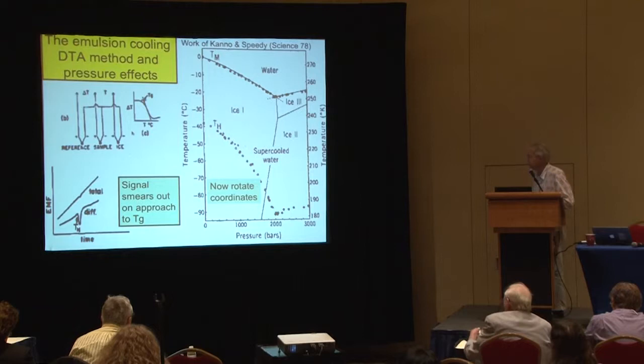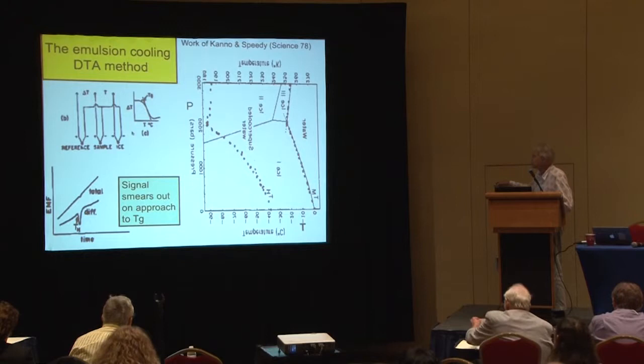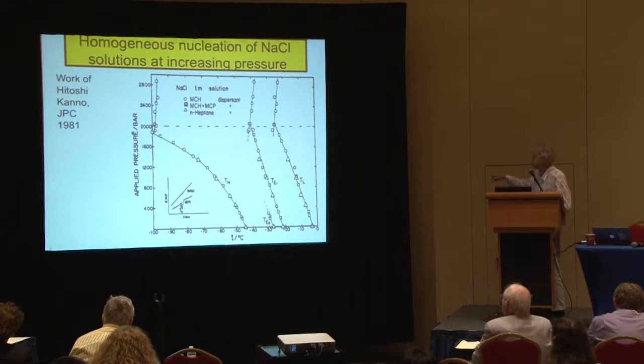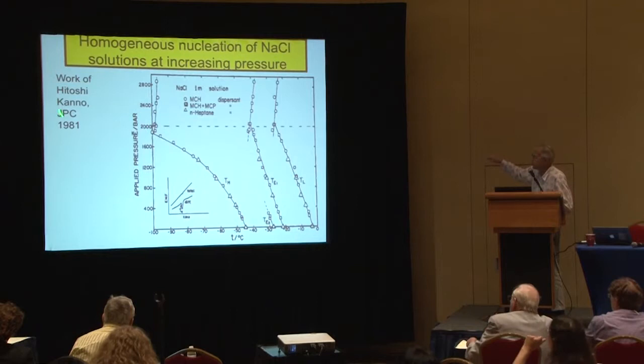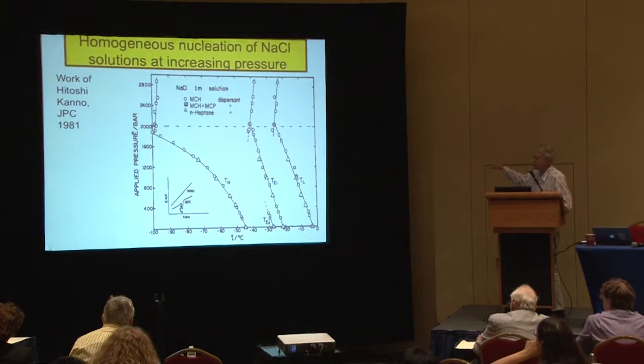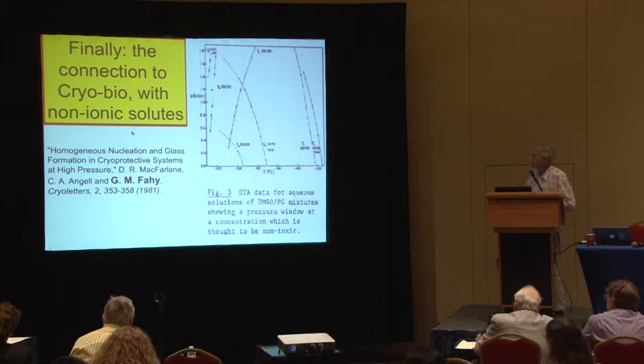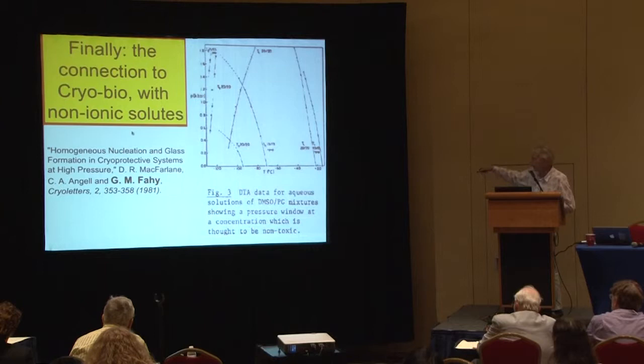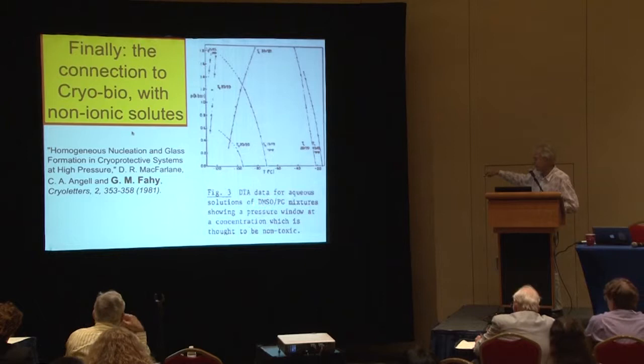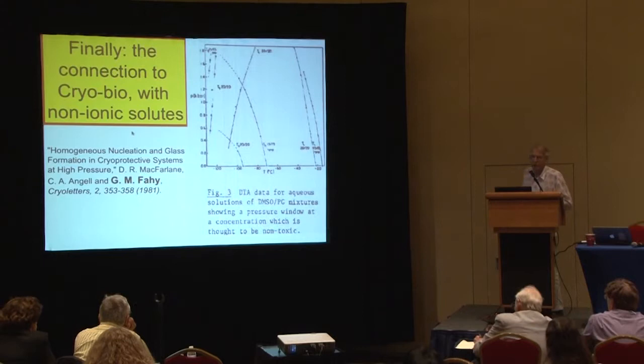You can see a minimum in the T1 spin lattice relaxation time if you're into NMR. So I've reoriented now to get pressure on the vertical axis, everything else the same, because this is where we got involved with Greg after some preliminary measurements by Hitoshi Kanno on the depression of the homogeneous nucleation temperature by pressure. And we were doing this for purely academic reasons, but then Greg, with Doug McFarlane, who joined us a little later, saw the importance of pressure in the cryobiological world. And so with his collaboration and advice, we looked at non-ionic solutes like DMSO and PG in this particular case, and found the pressures at which we could completely suppress the nucleation of water for these different combinations of solutes.